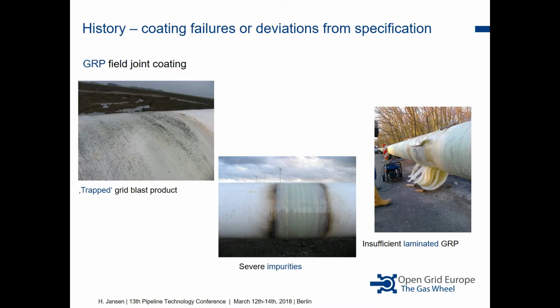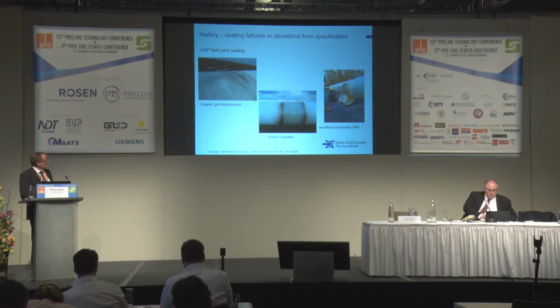and you may not detect some pores or coating defects with the holiday detection, but what you will get in these areas is a conductive path to the steel surface, and it will give some amount of CP current for the later CP system, and we will see later that these impurities will give a certain percentage of current pickup of the entire coating system.